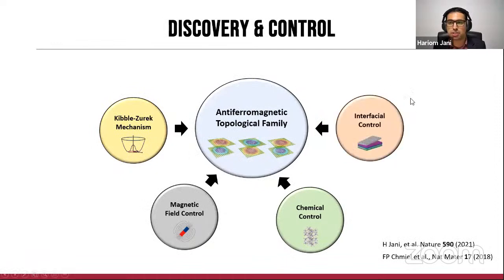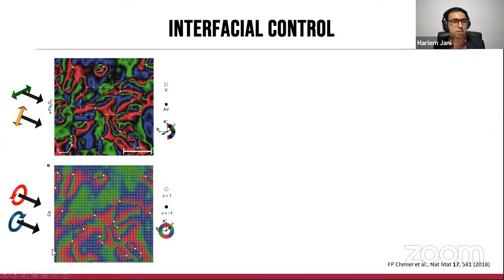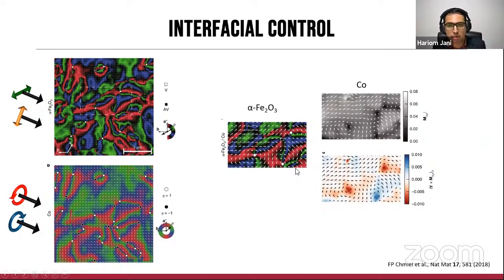Then we come to a crucial part, which is interfacial control. All the textures that I showed you so far were actually having a platinum overlayer, as I mentioned earlier, but instead it is possible to use a ferromagnetic overlayer. This was actually done previously by the Rodriguez group, and what they observed was that any topological textures are actually imprinted onto the ferromagnet by an interfacial exchange mechanism. I'm just zooming into a very small region here to actually show how the RGB texture, which is actually mapped by the same process, corresponds very closely to the arrows.